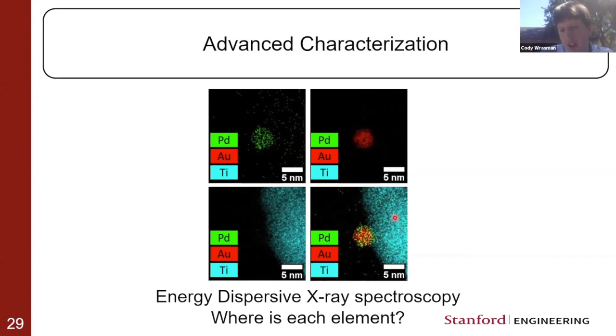So if you put them all together in one image, you see that the palladium and gold are actually located in the same nanoparticle. So this technique gives us a really cool way to visualize where these different elements are located within the catalyst.